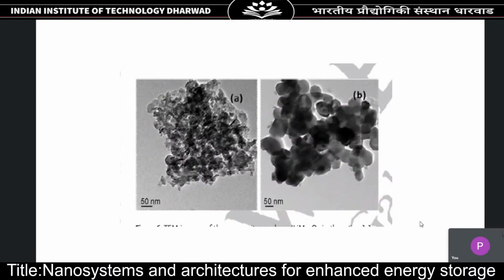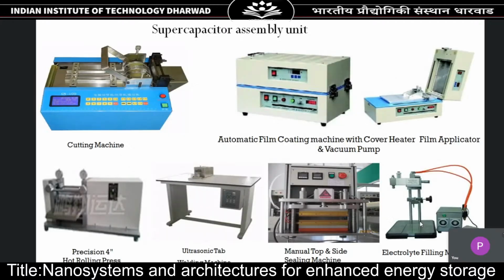This is a TEM image of the composite where the graphene was coated on the lithium manganese oxide. Some of these devices were made using an assembly unit, called the supercapacitor assembly unit. It has different subcomponents like a cutting machine, a film coating machine, a film applicator, a hot rolling press, a welding machine, and an electrolyte filling machine. So this all comes in a single package.